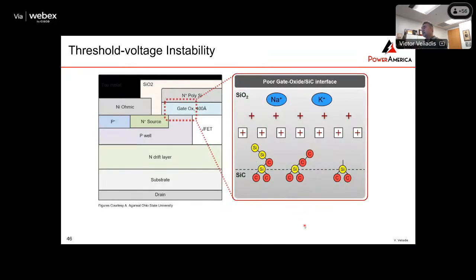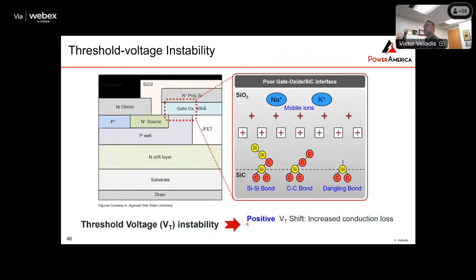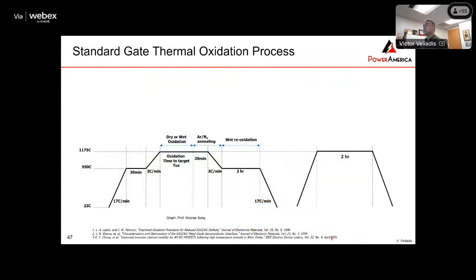So what is threshold voltage instability? You can see here that this layer right here has a lot of silicon to silicon bonds. It's got carbon-carbon bonds. It's got dangling bonds. And then you have these mobile ions. All these things contribute to trapping electrons and reducing the mobility. Threshold voltage instability means that if you bias the device in a certain way, you increase the conduction losses because you increase the threshold voltage. If you bias it in the opposite way, then the threshold voltage gets reduced, and that's very dangerous because now your threshold voltage is so low that an unintentional spike, like noise, can turn on the device.